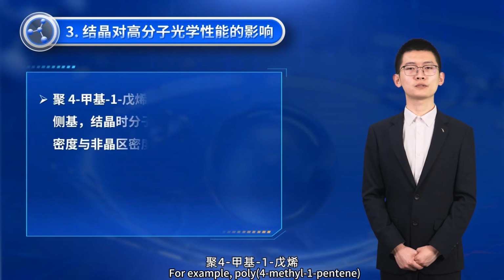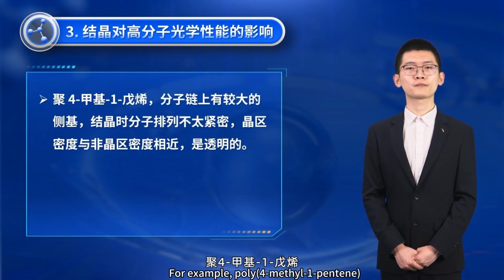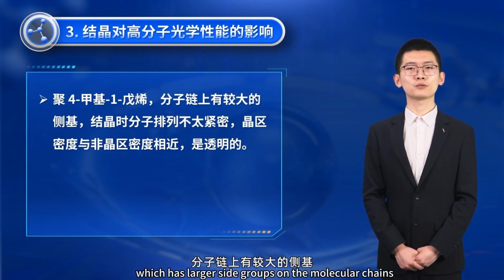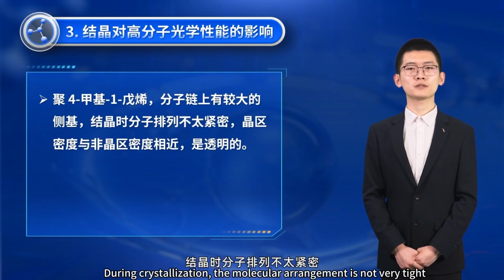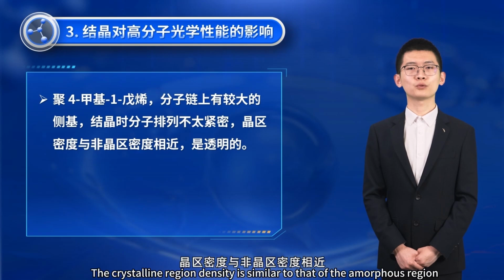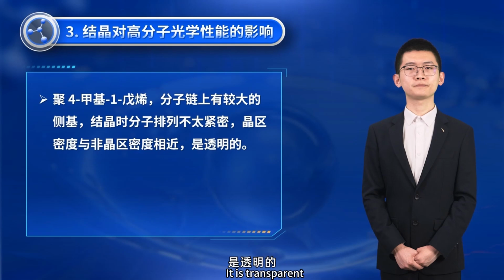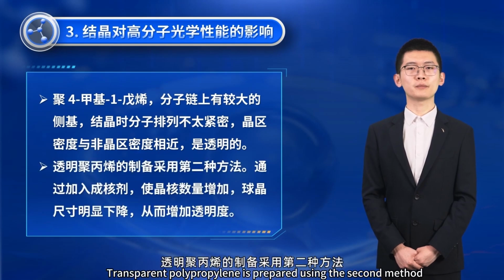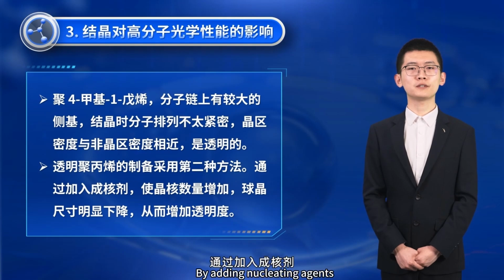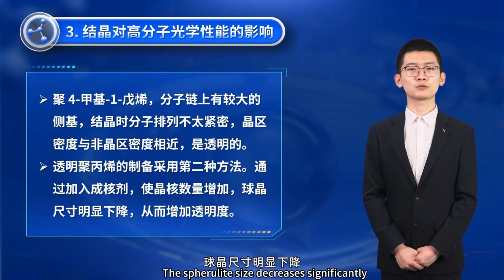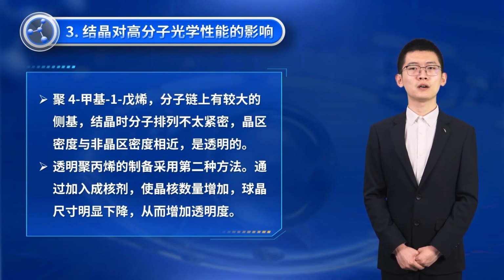For example, poly-4-methyl-1-pentene, which has larger side groups on the molecular chains. During crystallization, the molecular arrangement is not very tight. The crystalline region density is similar to that of the amorphous region. It is transparent. Transparent polypropylene is prepared using the second method. By adding nucleating agents, the number of crystal nuclei increases. The spherulite size decreases significantly, thereby increasing transparency.